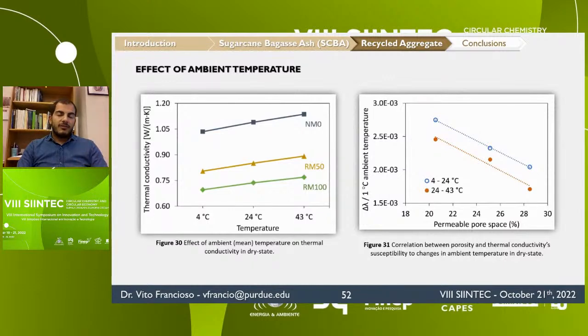Regarding the effect of ambient temperature, the most important result is that the higher the porosity, so the higher the recycled concrete aggregate content, the less susceptible the recycled mortar is to changes at higher ambient temperature.